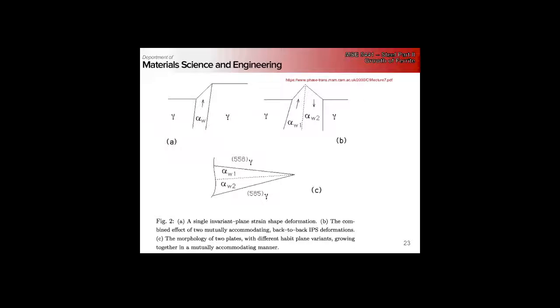You can imagine a deck of cards, and I offset one card next to its neighbor by a small amount. But if I do that for every card, that shear just builds up and up and up. Eventually, if I take that small shear across the whole deck of cards, I've got a big displacement from one side to the other. So this is happening, and energetically...